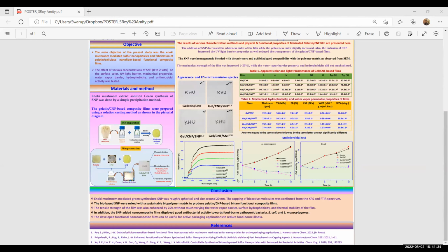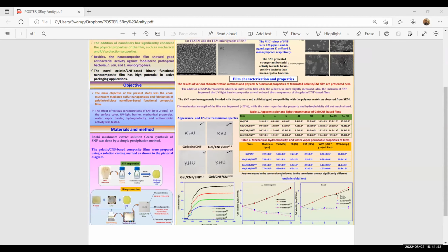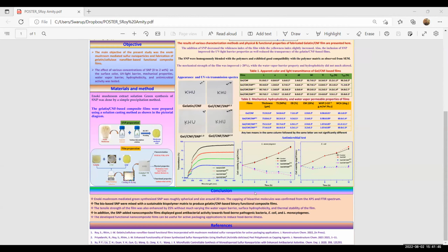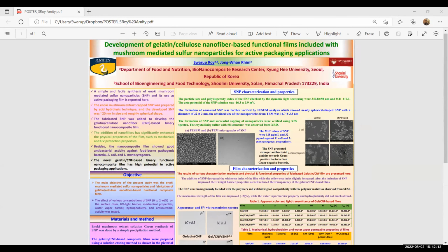So the enoki mushroom mediated sulfur nanoparticle can be synthesized using this simple precipitation method, and the bio-based sulfur nanoparticle can be a reinforcing material for the production of gelatin, cellulose nanofiber binary functional composite film. The tensile strength was enhanced about 25% without changing the water vapor barrier and other properties. In addition, the sulfur nanoparticle added film showed good antibacterial activity towards foodborne pathogenic bacteria, so it can be used as an active packaging material. Thank you.